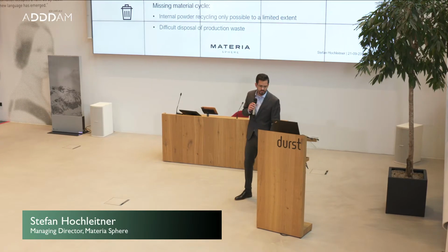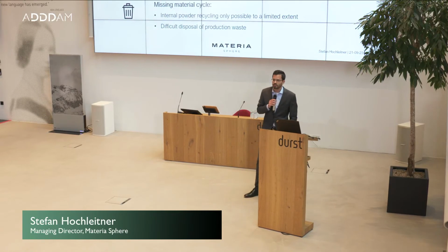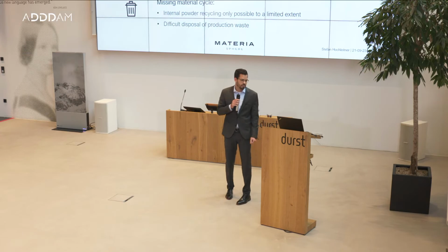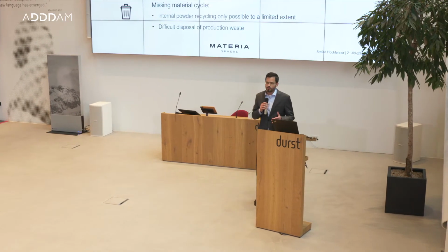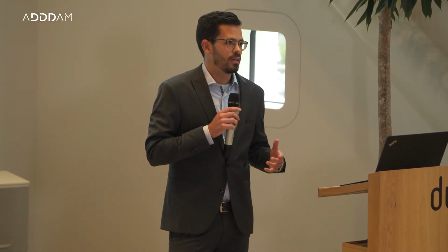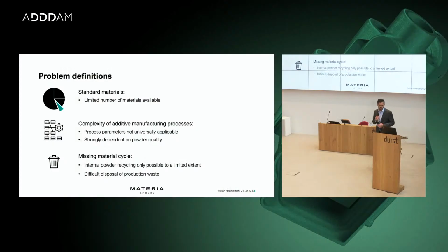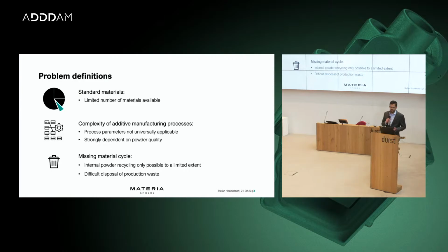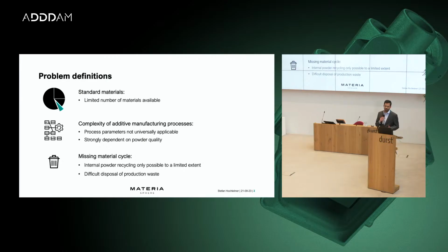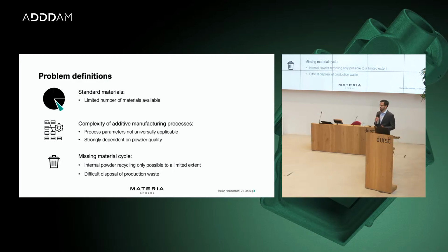As things go, it all started out with some problems, some difficulties we had during our research time at the University of Innsbruck. We found that we wanted to use a special material for laser beam powder bed fusion, but the material that we wanted to use was not available yet. So we found that the material number is still a limiting factor to the production. Also, the manufacturing process itself is highly complex, and you can't use, let's say, steel parameters for the production of aluminum alloys and so on. And it's also strongly dependent on the powder quality itself.